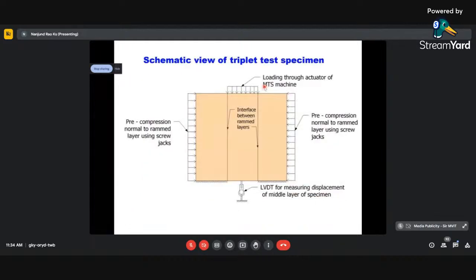So this is the triplet shear specimen. Now you will very clearly see this is the layer, compacting layer 1, then compacting layer 2, but actually we rotate it at the time of preparing the specimen or casting, and at the time of testing we rotate it by 90 degrees and we support the end ones here. What you see is supported, and we also give a normal compression, and we only push through a servo hydraulic actuator system, MTS, the middle one. Now, this pre-compression is given in different amounts for different specimens in order to get the Mohr-Coulomb parameters, that is C and phi, which is related to the shear strength, that is the interface shear. And we also measure the slip of the middle one with an LVDT as the load is applied.